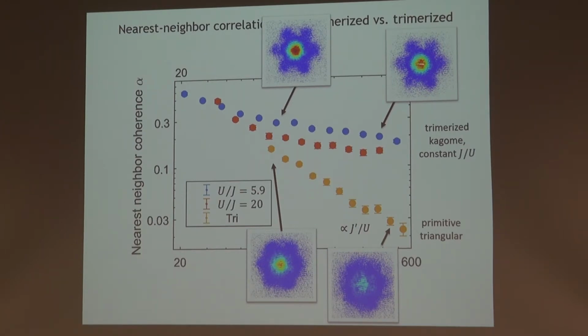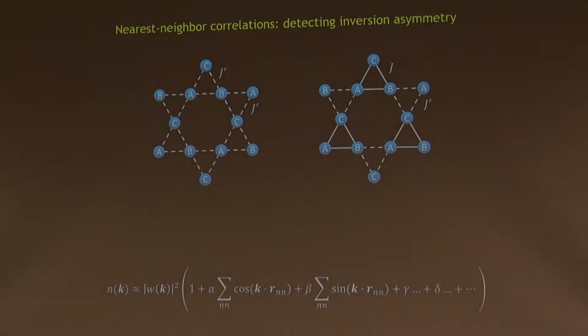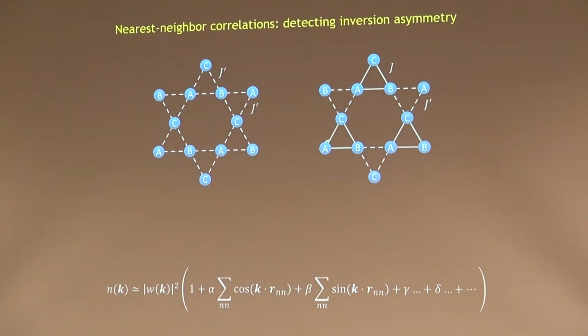There's a second aspect of these images that we're only now realizing, we should have realized a while ago, that the breathing, the displacement of sites in the Kagome lattice, is also, in the trimerized Kagome lattice, visible in these images. And actually, we have to correct some of our data from this slide upwards because of that effect. OK, but the persistence of nearest neighbor coherence in this lattice doesn't really tell us everything, because we were trying to develop the story that the coherence exists on one of the bonds of the lattice, but not the other bond of the lattice.